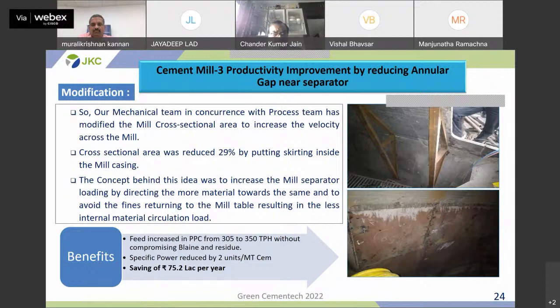By this, we have increased velocity in the separator, and dust loading of separator also increased by diverting material towards it. This avoids fines returning to the table, resulting in less internal material recirculation load. By this, we were able to increase our PPC feed from 305 to 350 TPH without compromising quality parameters. With this, specific power consumption got reduced by 2 units per ton of cement and savings of 75 lakhs per year.